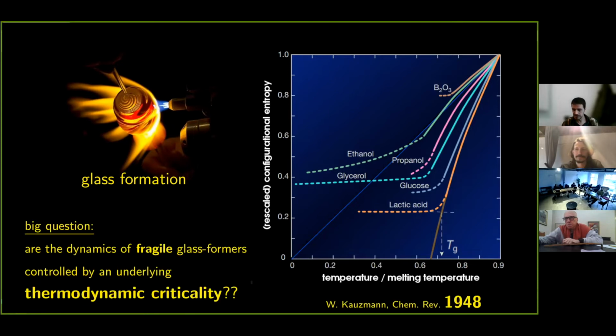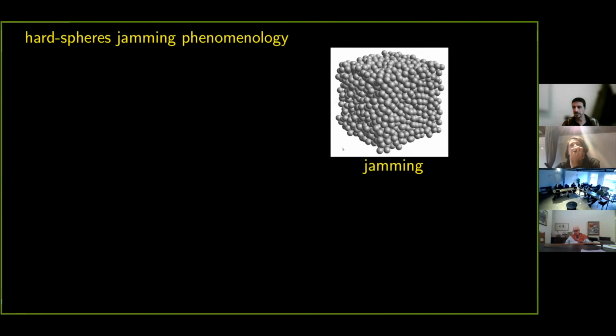And what you see is that for some of the fragile liquids, if you plot this observable as a function of the temperature, it seems to extrapolate to zero at a finite temperature. And this was one of the big mysteries that came out of experiments on liquids and glasses. How is it possible that the configurational entropy vanishes at a finite temperature? It cannot become lower than the crystal entropy. So that is about glass formation.